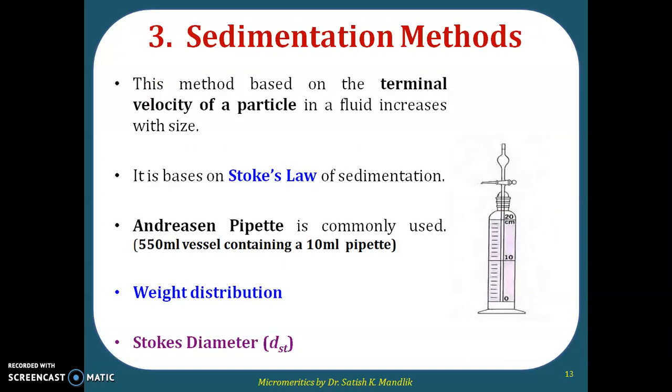Sedimentation method. This method is based on terminal velocity of particle in a fluid which increases with size. It is based on Stokes' law of sedimentation. Andreasen pipette is commonly used in sedimentation method, which is official in different pharmacopoeias. It is a 550 ml glass vessel which contains a 10 ml pipette for withdrawal of samples.